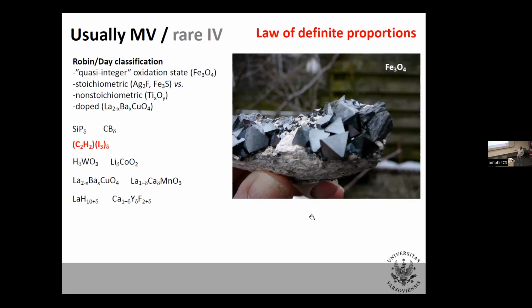For example, there is a compound Ag2F. It's not AgF2, of course, which I showed before. It's Ag2F. That's a really well-known compound. What is the oxidation state of silver there? Well, one should say half plus. But someone would say, okay, for sure, there must be silver 0 and silver plus in there. But you look at the crystal structure, and it's not so. Every silver is equivalent to another silver. And therefore, the real oxidation state is half plus.